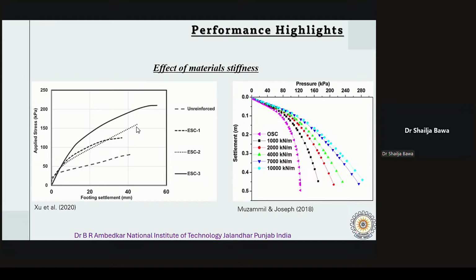The pink curve is for ordinary stone columns and they settle more under pressure. And as the stiffness of the encasement increases from 1000 to 10,000 kilonewton per meter, curves shift to the right, indicating lower settlement under the same pressure. So this means that as we increase the stiffness of the geosynthetic material, the column becomes more effective at resisting pressure and minimizing the settlements. So the key takeaway from both the graphs is simple: the stiffer the encasement, the better the performance in terms of both bearing capacity and settlement control.